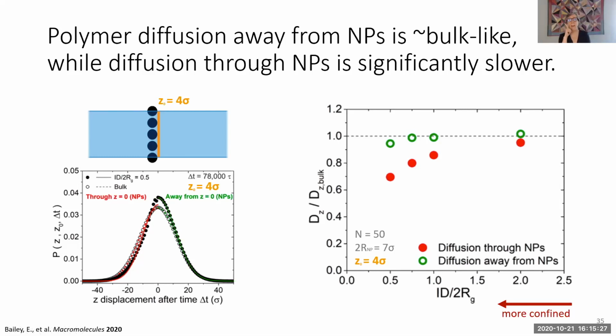And that's interesting because when we were in confinement, we know that there's a change in the chain conformation. So there'll be fewer entanglements where the particles are. It's less entangled there, and you would suspect that would give a faster diffusion coefficient. But because of additional factors, the distortions to the chain conformation more wholly, not just the loss of the entanglements, we can see that the diffusion coefficient going into the monolayer is actually depressed. It's moving slower.